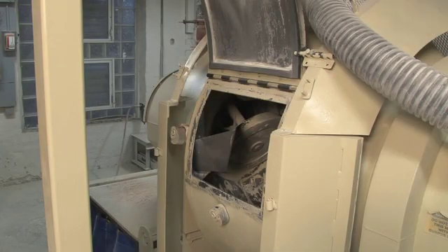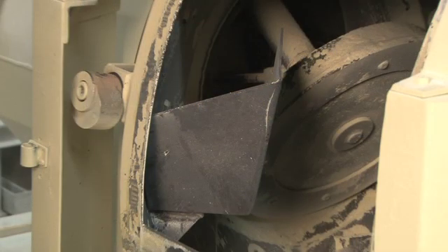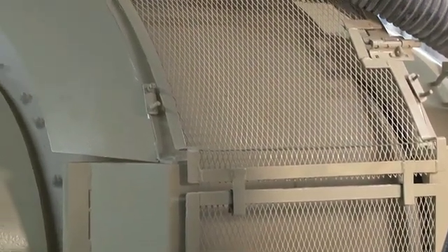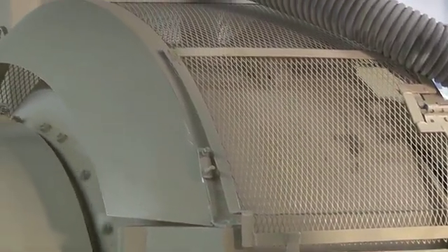The liner and other contact surfaces in the rotary mixer are made of abrasion-resistant steel designed to withstand the abrasive mixture, particularly sand. Mixing times are only about five minutes, less than half the time required by the pan mixer.